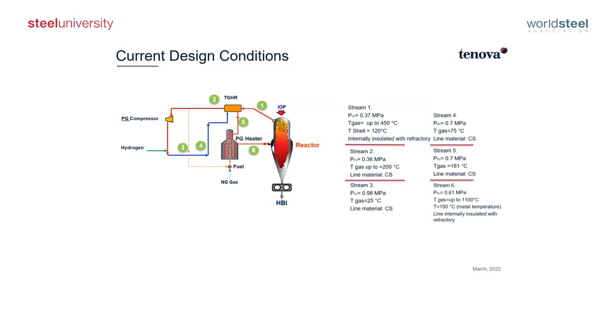gas heater, inside the process gas heater, because in all tubes, ducting, even the reactor itself, you never reach these high temperature and high pressure conditions. Even though the reaction inside the reactor reaches 1,000 degrees, the reactor is refractory lined, and the surface of the reactor, meaning the metal itself, never reaches 200 degrees. You can always touch the reactor with a glove, but it never reaches 200 degrees. So most of the construction didn't need any modification when we began designing modules expressly conceived for working with 100% hydrogen, because we were already there.